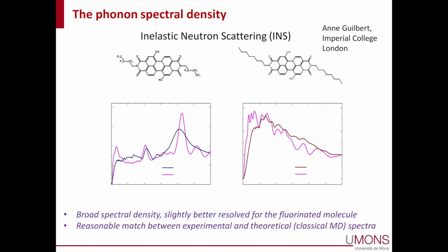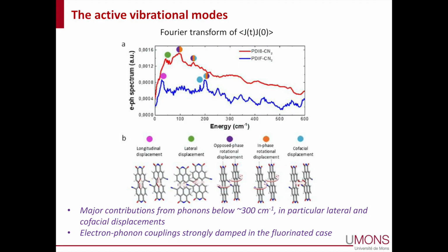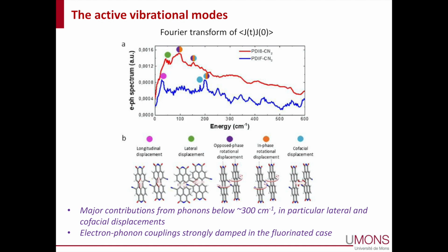But essentially, what this tells us is that we are able to reproduce correctly the phonons in those systems. So which phonon dominates can be captured by tracking, for instance, the transfer integral between nearest neighbors. And we do this in the time domain. So you can compute the autocorrelation function of the transfer integral, and if you Fourier transform that autocorrelation function, you end up with a spectrum, where the x-axis tells you something about the frequency of the modes that contribute, and the intensity is a measure of the electron-phonon coupling.